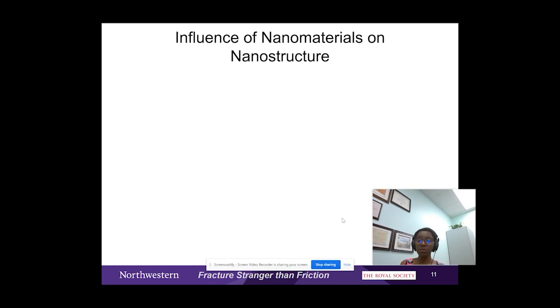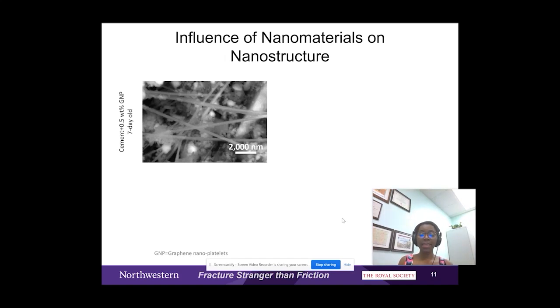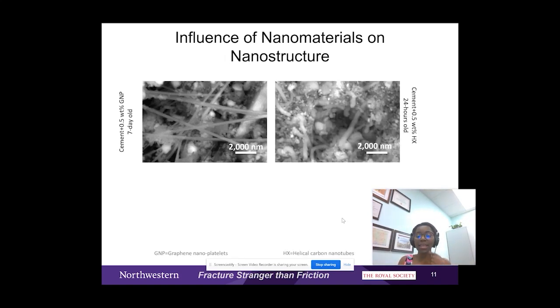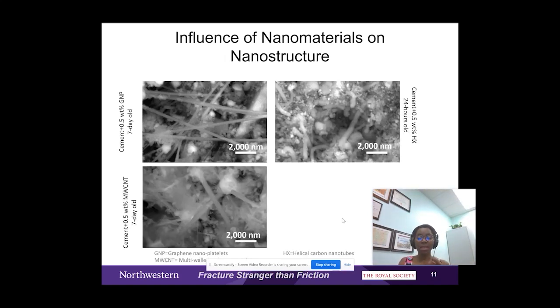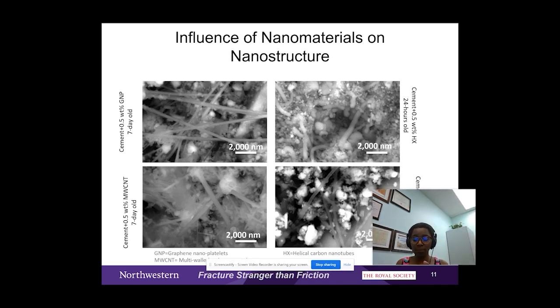Then I use high-resolution scanning electron microscopy to understand how nanomaterials interact with cement hydration products. And I looked at graphene cement, I looked at helical carbon nanotube cement, multiwall carbon nanotube cement, and carbon nanofiber. And what I saw is that nanomaterials tend to bridge nanoscale air voids and connect cement hydration products.